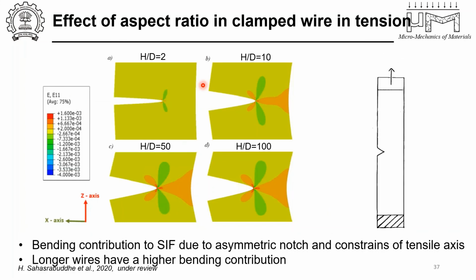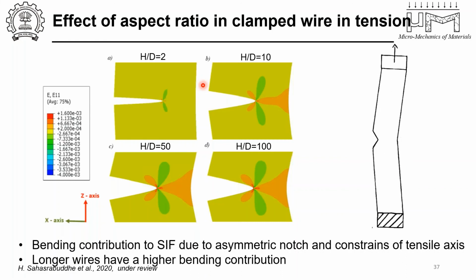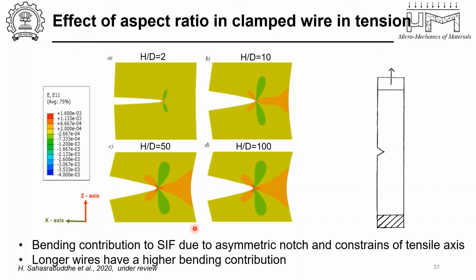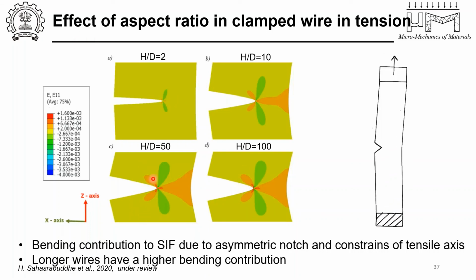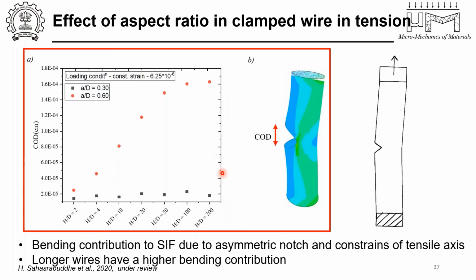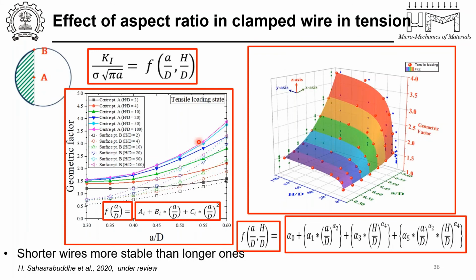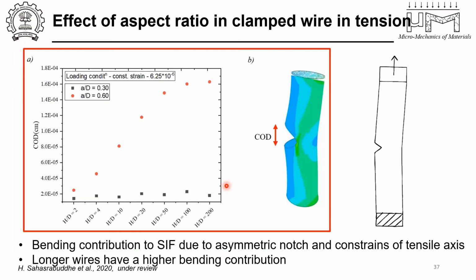So this is the conclusion we come to, that the asymmetric notch results in a bending superimposition on the tensile load, which is what results in the severe effect of the aspect ratio. But this plateaus at larger aspect ratios. So if you have very large aspect ratio wires, then you don't have to care about the H/D. This is something we also saw here, that they plateau and fall on top of each other when you have higher H/Ds, but it becomes important when you go to lower H/D values.